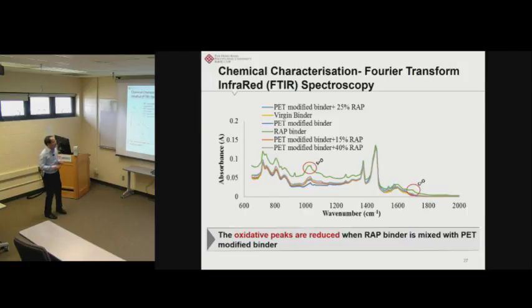Now if we take a look at the other binder samples, the PET modified binder is this dark blue one, which is at the relatively bottom part. For the PET modified binder, we can see these two peaks, their amplitude are significantly reduced, especially for the CO double bond peak. We can actually hardly see the peak. Even with the RAP binder added, this peak is not that significant. For the SO double bond, yes, there's still some peak, but it's much less significant compared with the RAP binder.